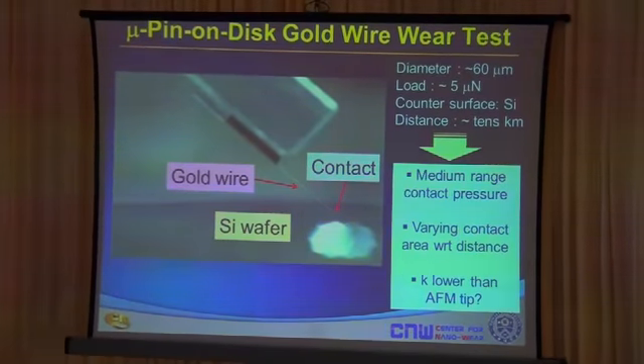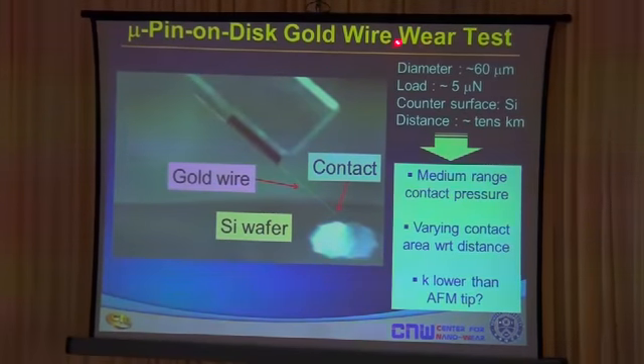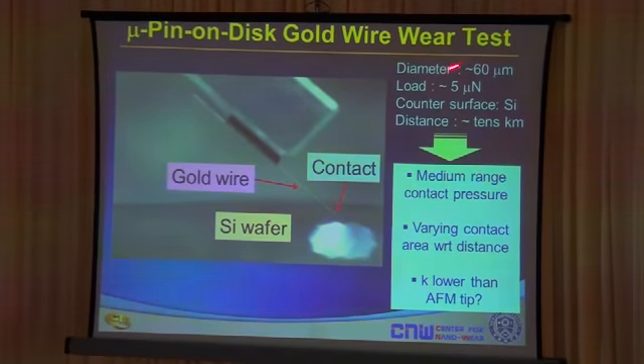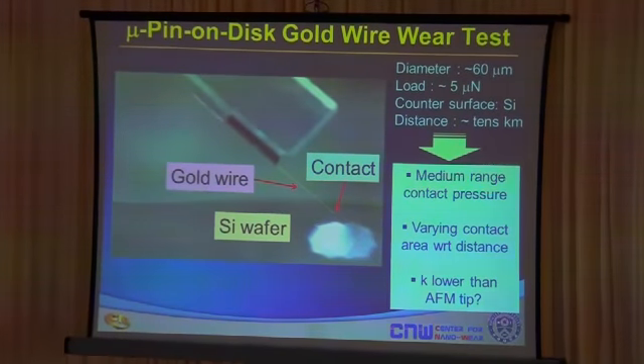Now, to go into somewhere between the atomic force microscopy and bushing, what we did was to create what we call one of the smallest pin-on-disc type of experiment. Here what you're looking at is a gold wire wear test. Diameter of the gold wire was about 60 micrometers. I don't know if you can see this, but that's the gold wire. It is contacted against a silicon wafer at an angle. And this gold wire was very carefully prepared so that it's relatively straight and the edge is flat.